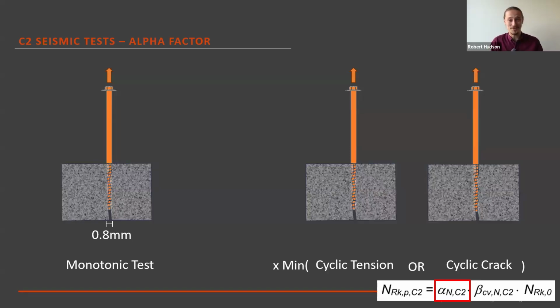But this was based on a really nice piece of research that was done, again, same kind of time in California. All of this really comes out of there, or the University of Stuttgart. What they did is they built a reinforced concrete frame. They put a simulated non-structural element underneath the reinforced concrete beam. They put it through thousands of cycles, and they measured across time the tension in the anchors and the crack widths. And basically what they found is that the maximum of each don't occur at the same time. And so when we're generating these capacities, when we talk about tension, we just account for whichever one has the most adverse impact.